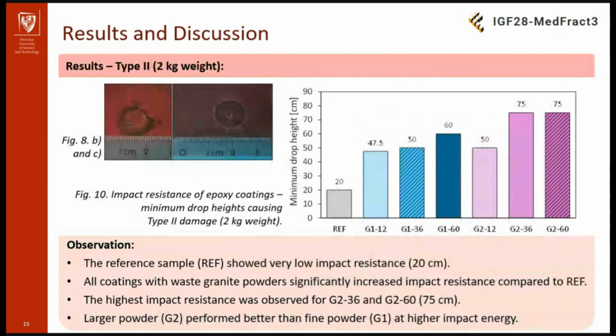Here you can see the results for type 2 damage with the 2 kilogram weight. The reference samples showed a very low impact resistance, only 20 centimeters. All coatings with the powders significantly increased the impact resistance. The best results were observed for G236 and G260, the powder with the larger fraction.